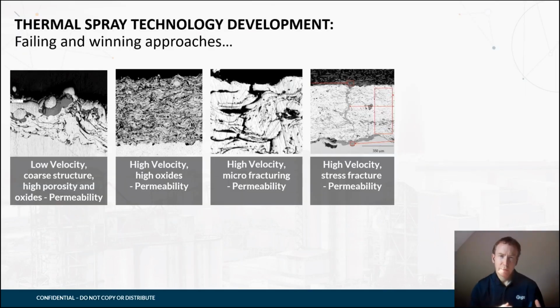So when we're thinking about thermal spray for application in these conditions, we need to consider that we're creating an impermeable barrier with that thermal spray process. So we're using an alloy, a C276 alloy, but we're putting it through a highly aggressive application procedure. We're melting it in the thermal spray gun. We're then projecting it through the atmosphere onto the surface. So there can be lots of changes to that alloy unless we control the application process, unless we control the alloy itself.